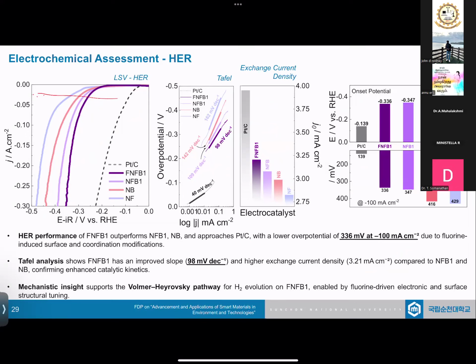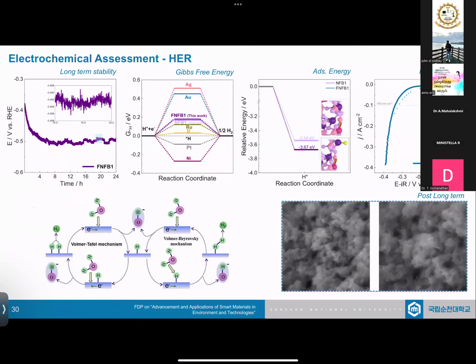We know the fluorine altering the system has changed the material, but still the question is how and why did this happen? So we have to answer it through mechanistic insight, where we need to evaluate the Volmer-Heyrovsky pathway based on the Tafel values that we got. What we do is we evaluate theoretically, trying to attach a hydrogen atom into the system, and we find out its Gibbs free energy and its adsorption energy.